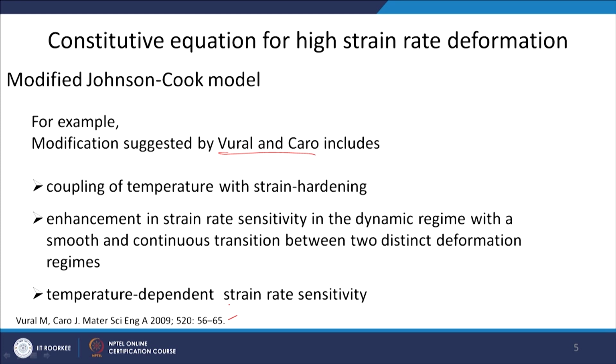Enhancement in strain rate sensitivity in the dynamic regime, with a smooth and continuous transition between two distinct deformation regimes. Okay. So, strain rate sensitivity is also going to be affected in the dynamic regime, and there will be a temperature dependent strain rate sensitivity also. So, you should understand that these parameters are all coupled to each other. So, we cannot treat them independently, and there are a lot of modifications proposed by different researchers on the Johnson-Cook model.